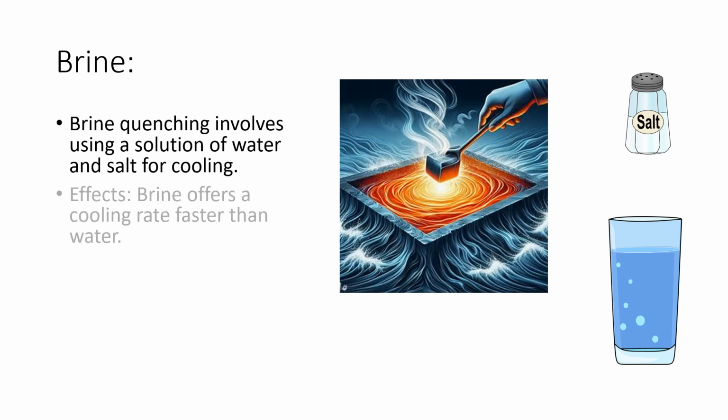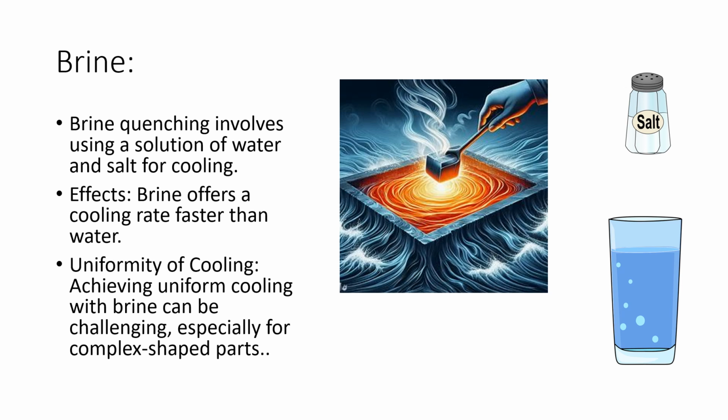The thing about this stuff is brine offers a cooling rate that is faster than water, about double. This is going to help your hardness, but there's a whole other list of things you've got to think about in regards to uniformity of cooling. With brine, it can be challenging, especially if we've got really complex parts. You can end up with cracking.